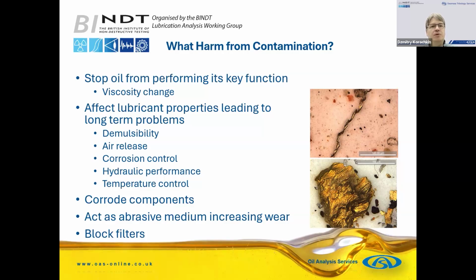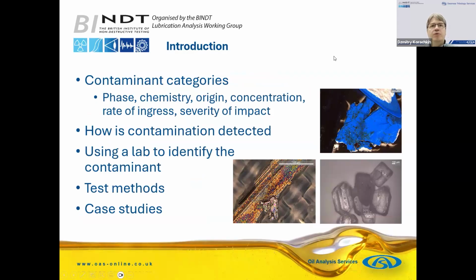Contaminants can corrode components, and a lot of the time when we talk about contaminants, we also mean particles, where debris becomes a contaminant itself once it's generated. So those can act as an abrasive medium, increasing wear. And contamination can also cause filter blockages, which can then cause oil to go through bypass and cause all sorts of problems. And generally, a lot of machine failure is caused by poor lubrication, and contamination is a significant contributor to poor lubrication.